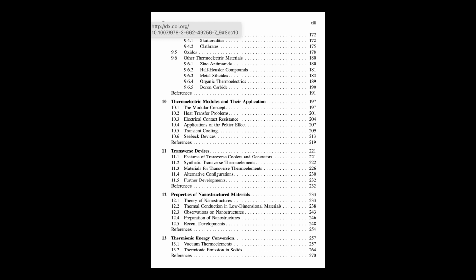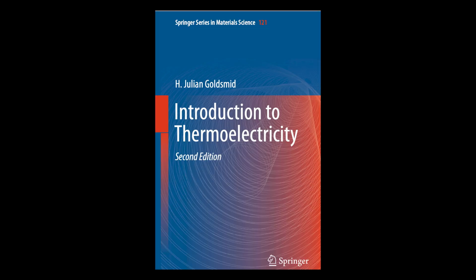It requires careful temperature control and sensitive voltmeters. Sometimes they use chopped heat sources and measure the resulting AC voltage. Tricky. And thermal conductivity. Isolating heat flow sounds hard. It is. Several ways. Steady state methods. Apply known heat power, wait for temps to stabilize, measure the gradient, calculate lambda.